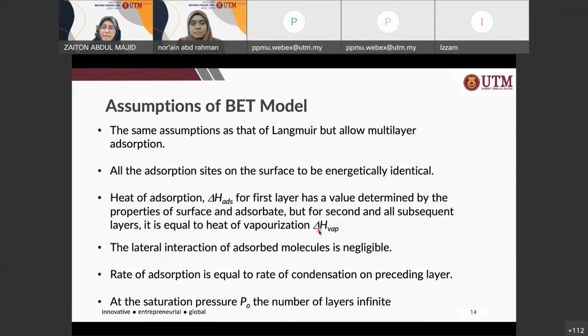So basically, when you have adsorption, you're actually talking about the liquid state rather than the gaseous state. So the heat of adsorption, delta H adsorption, for the first layer has a value determined by the properties of the surface and the adsorbate. So it depends on the nature of your surface and also the nature of your adsorbate gas, whether the interactions are strong or weak. That depends on the properties of your surface. But for the second and all subsequent layers, it is equal to the heat of vaporization of that adsorbate gas.